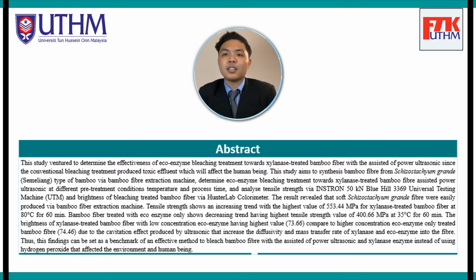The result revealed that soft Schizostachyum grande fiber was easily produced via the bamboo fiber extraction machine. Tensile strength shows an increasing trend with the highest value of 553.44 MPa for XYLANASE-treated bamboo fiber at 80 degrees Celsius for 60 minutes. Bamboo fiber treated with ECO-ENZYME shows a decreasing trend with the highest tensile strength value of 400.66 MPa at 35 degrees Celsius for 60 minutes.